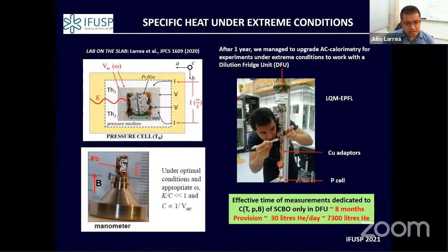Another interesting point here is that I represented the pressure cell, but it's coupled thermally to the cold finger of the dilution fridge through different pieces made of copper. And everyone knows that copper works with magnetism, so when you apply a magnetic field, you produce eddy currents. These eddy currents can disturb your experiment, so we have another issue to sort out, and this is what we managed to do, to diminish the influence of the eddy current in our experiment.